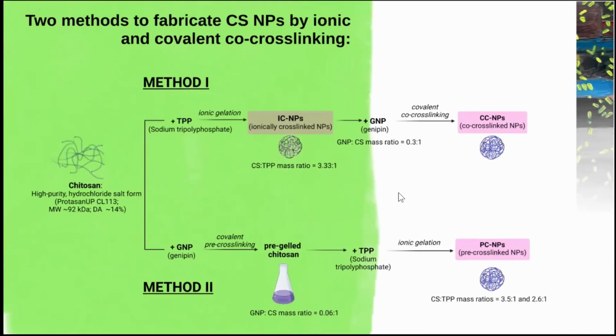So we have developed 3 types of nanoparticles, namely IC or ionically cross-linked nanoparticles, CC genipin co-cross-linked nanoparticles, and PC genipin pre-cross-linked nanoparticles, prepared by 2 fabrication methods that are represented here in this scheme. The starting material was a commercial Chitosan of high purity in the hydrochloride salt form with an intermediate molecular weight and a degree of acetylation of 14%. Method 1 is initiated by ionic gelation of Chitosan with TPP to render the ionically cross-linked nanoparticles by the method developed in our group in Santiago, followed by genipin covalent co-cross-linking to render the co-cross-linked nanoparticles.